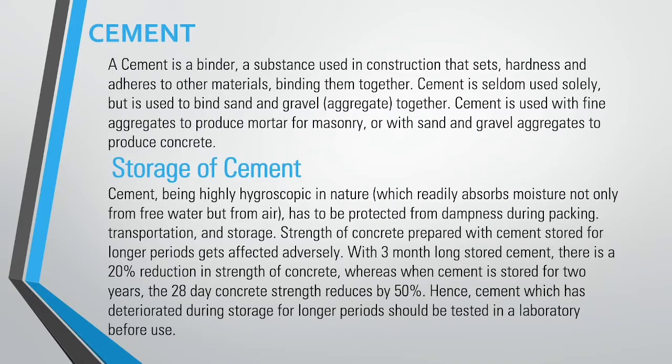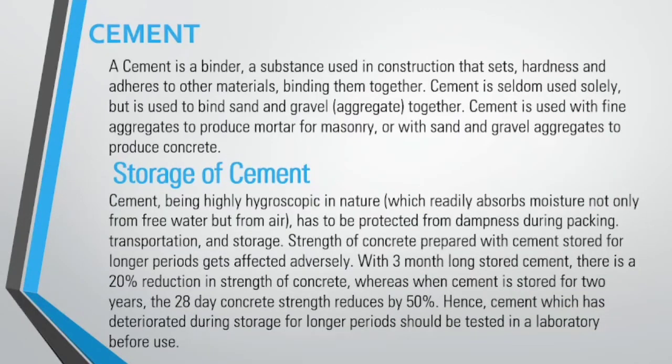there is a 20% reduction in strength of concrete. Whereas when cement is stored for 2 years, the concrete strength is reduced by 50%. Hence, cement which has deteriorated during storage for longer periods should be tested in a laboratory before use.